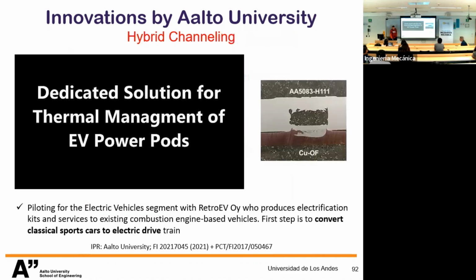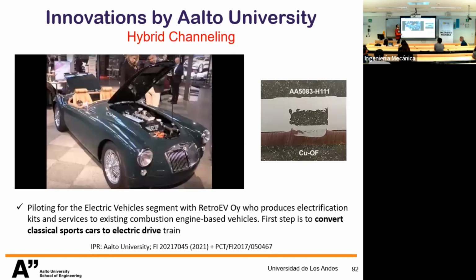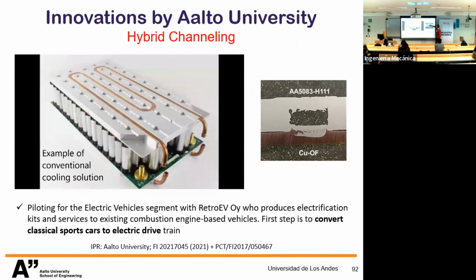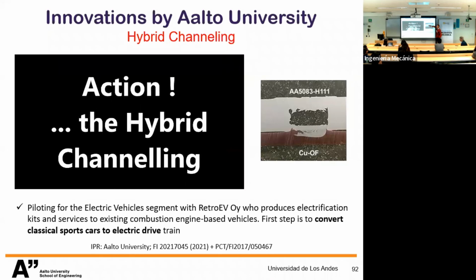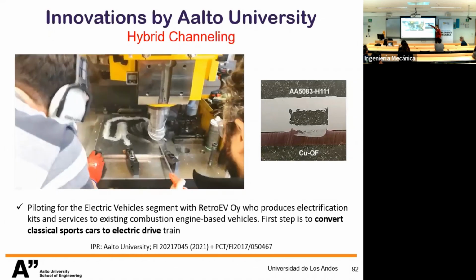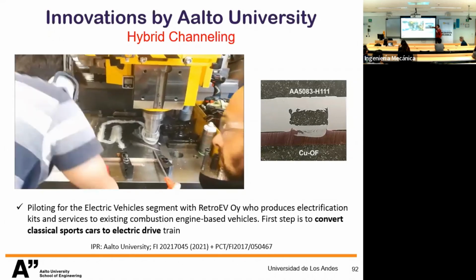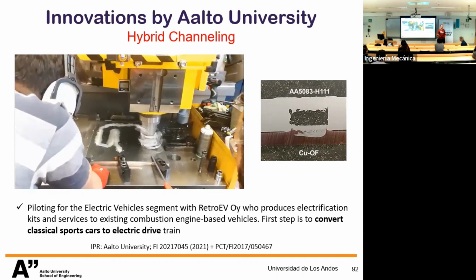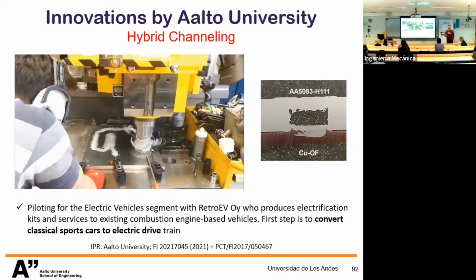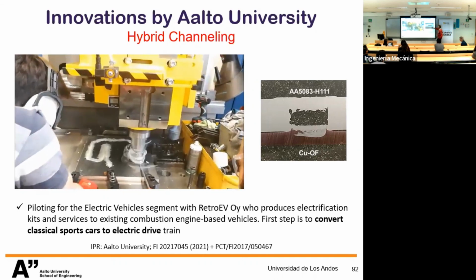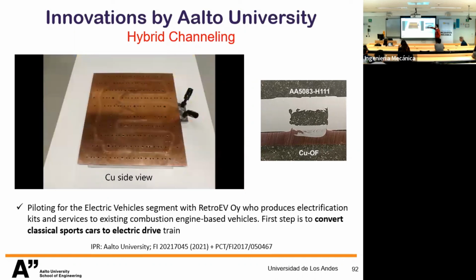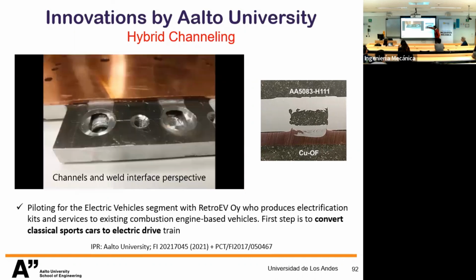Another example is the evolution of friction stir channeling that we saw. So now we produce channels, but we also are able to weld different materials in the same operation. So we produce a channel in a bulk material and then a weld. With this, we combine the properties, and we can use copper that is expensive and heavy in a very thin sheet to do the thermal management of the system.